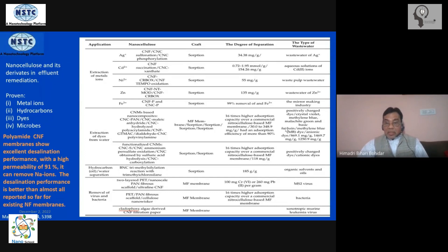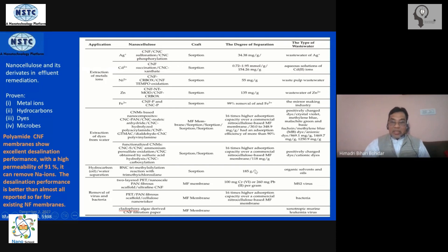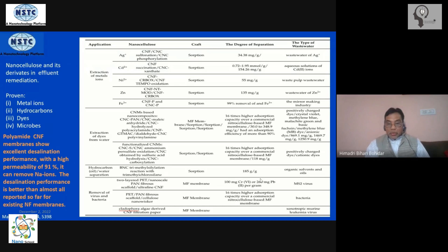If purity is maintained, it is easy to remove dyes from water using nano cellulose as a filtering mechanism. Next are hydrocarbons and oils separation. Particularly, bacterial nano cellulose shows the most efficiency here. The degree of oil separation can be as high as about 180 grams per gram, which is really huge. All these possibilities exist when using cellulose nanofibrils as an active agent for effluent treatment.